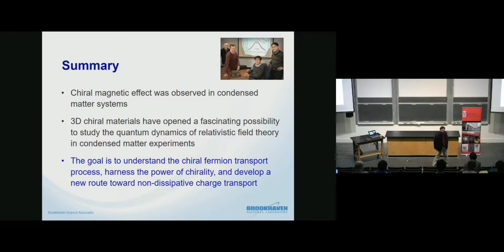Hi, Jeff. What is the typical resistivity at room temperature and also at 10 degrees Kelvin? Okay, that's a very good question. Actually, beats me. Because with these semimetals, the carrier density is so low, so actually it's not a good metal. So resistivity is in the milli-ohm centimeter range. Micro-ohm centimeter? Oh, no, milli-ohm centimeter. I'm sorry, micro-ohm, that's a good metal. Milli-ohm centimeter, that's why most of the topological materials are semimetals, semiconductors, thermoelectrics. They are really not good metals in there.